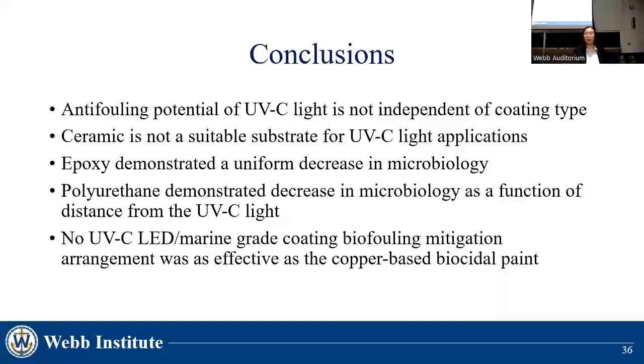The G-Technique ceramic coating selected was not a suitable substrate for UVC light anti-fouling applications. Epoxy and polyurethane remained potential avenues and showed advantages in the types and quantities of growth observed. Epoxy demonstrated a uniform decrease in microbiology levels observed, while polyurethane demonstrated a decrease in microbiology as a function of the distance from the UVC light diode.